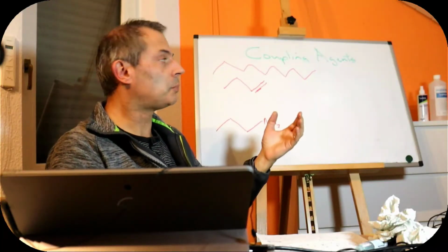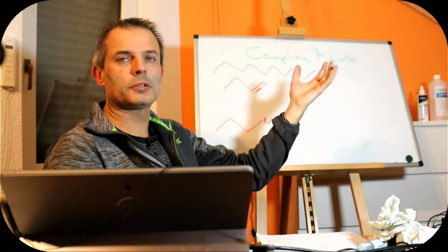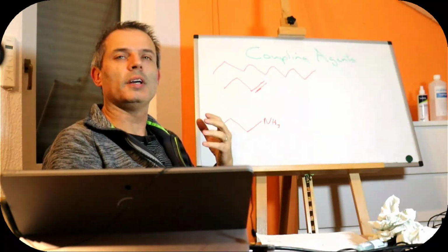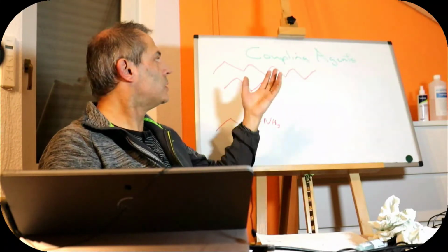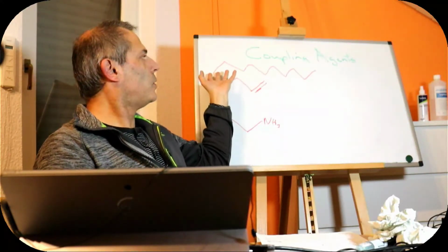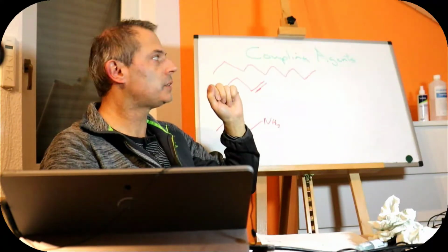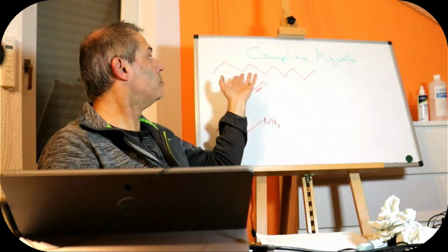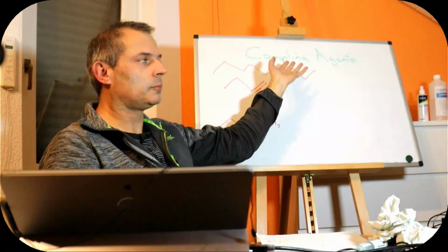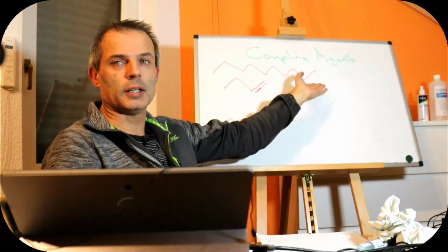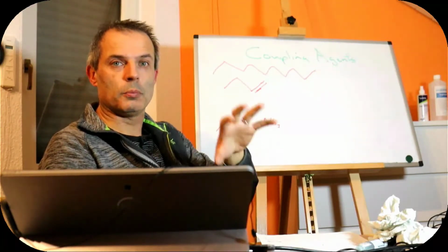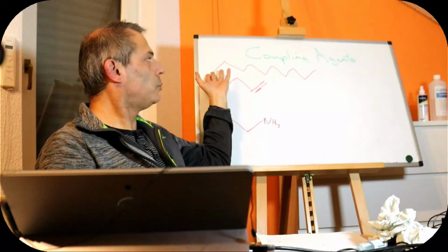Some of the more common coupling agents would be simple chain molecules to make it hydrophobic, which would be a way of getting things to dissolve into, suspend into organic solutions, which normally wouldn't, such as polymers, for example, and such as metal particles, which will then dissolve in organic solutions or suspend in them better. So if we want to make some paint, for example, we may have to treat our color particles, our inorganic color particles, with a silane that's got a long chain on it. For other purposes, if we want to have an additive to polymers, a filler material or anything, then we might also do the same thing.